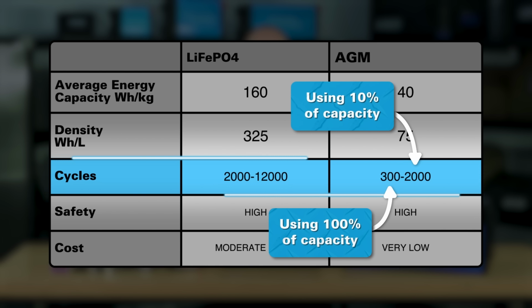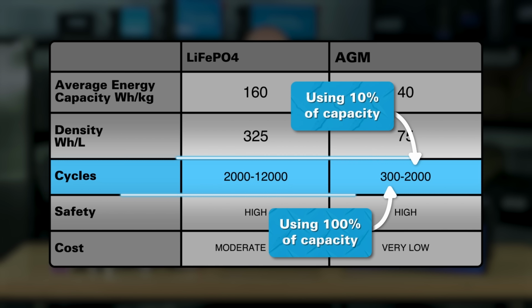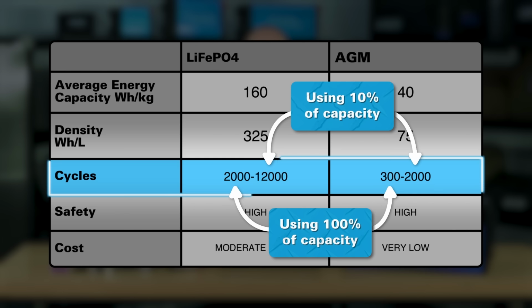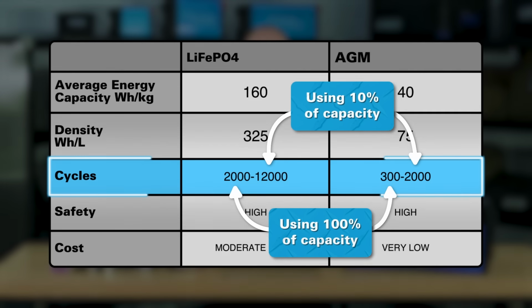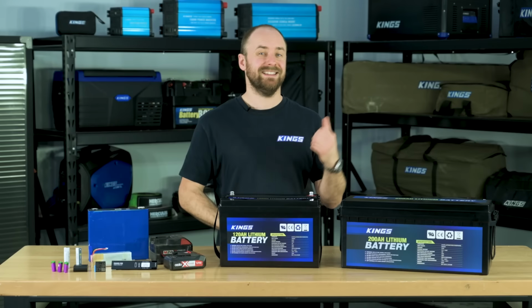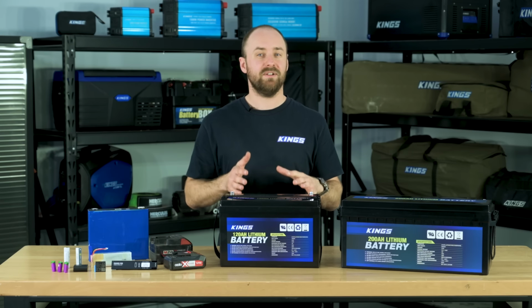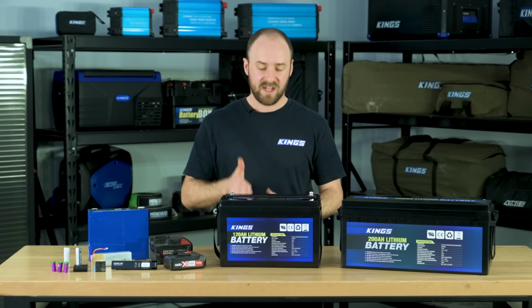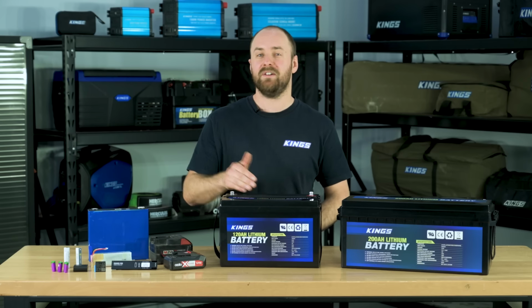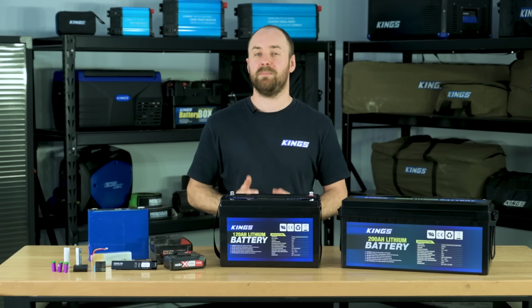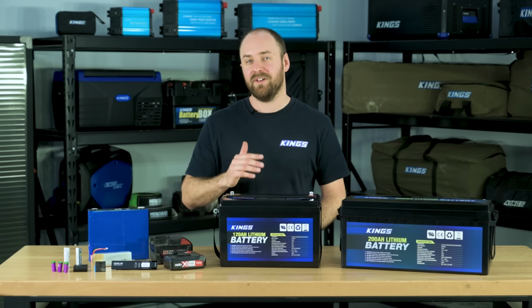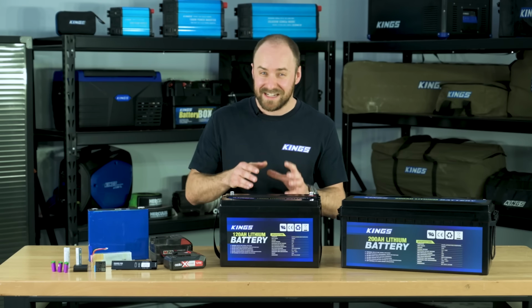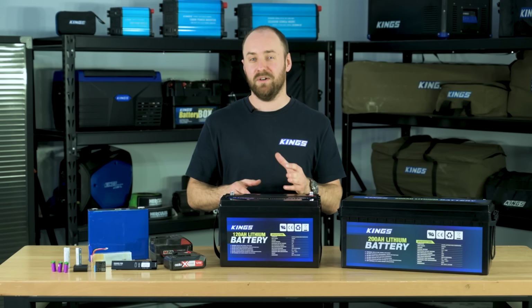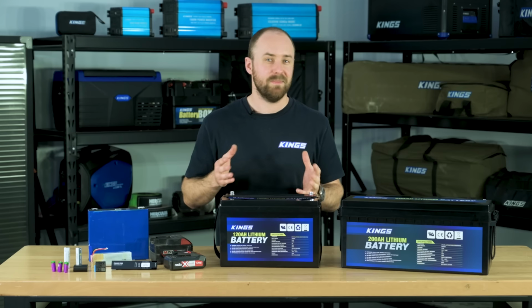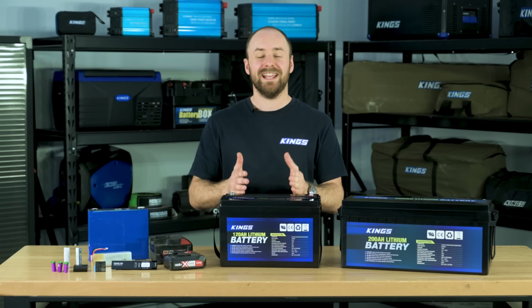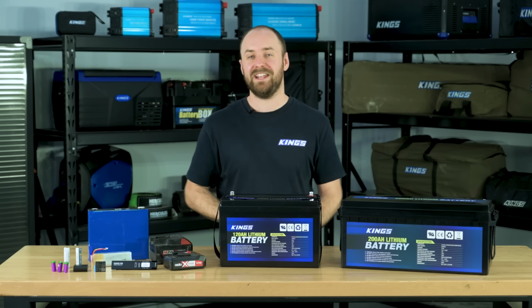On the other hand, a lithium iron phosphate battery can be discharged all the way to 0% and still get you around 2,000 cycles. So rather than lasting less than a year, or about 300 daily cycles with an AGM, if you used your lithium iron phosphate from 100% down to 0% repeatedly, it could last up to 5.5 years. And if you did only use the top 10% of a lithium iron phosphate battery, like we mentioned with an AGM, it'd probably outlast your vehicle and possibly even you.